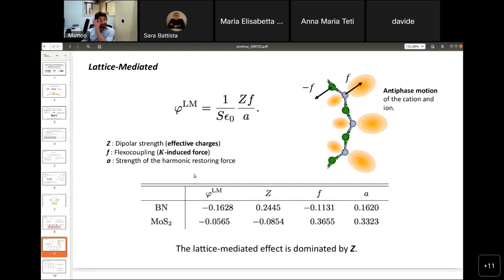If we look at the lattice-mediated effect, because of the symmetry of the systems considered, we find that internal relaxation corresponds to an antiphase motion of the atoms, which in turn can be seen as two ions described by opposite, equal charges. So basically we can see it just like the antiphase motion of a cation and an anion. So we have a more intuitive description of the lattice-mediated effect, which we can write by use of the effective charges describing the two ions, the flexural coupling, that in this case is the force induced on the ions because of the application of the curvature, and the harmonic restoring force.